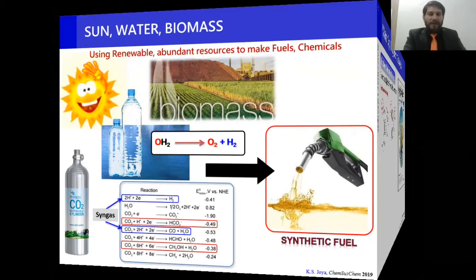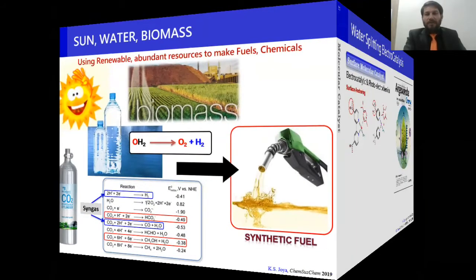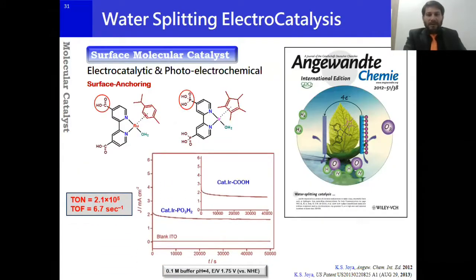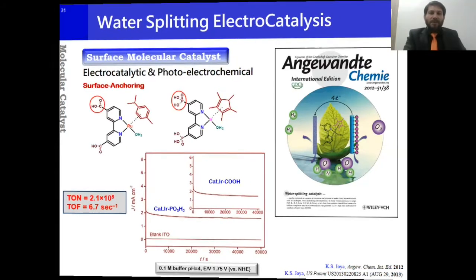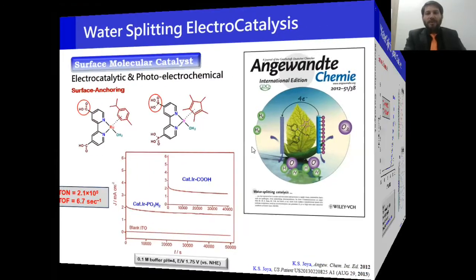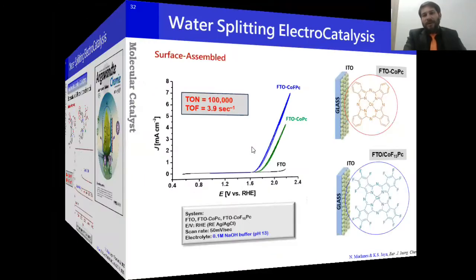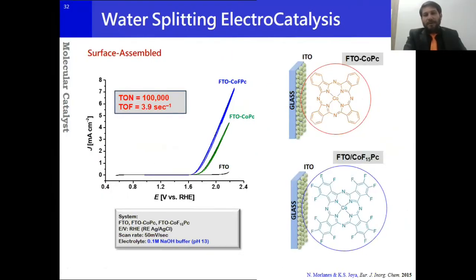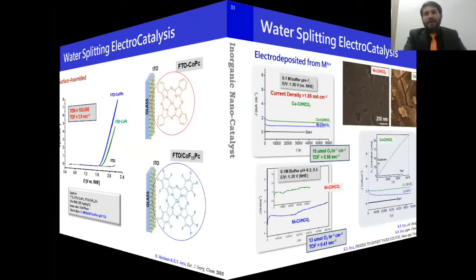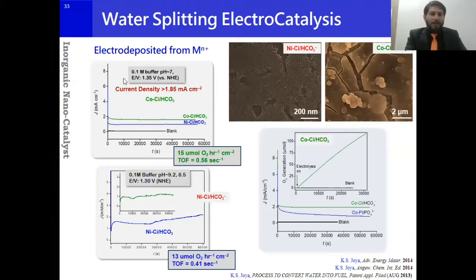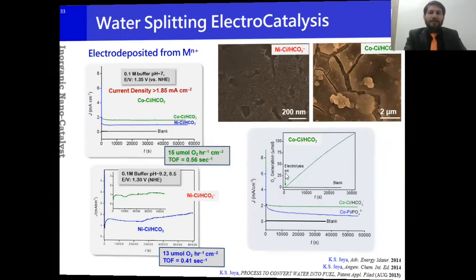So in water splitting, like I said before, we make this organic molecule, we functionalize them on the surfaces, and then we perform water splitting. In this case, you can see these are just molecules absorbed on the surfaces. They can also perform water splitting. And then these are electrodeposited metal oxides. In this case, you can see nickel and cobalt. And you can see from this figure, they perform wonderfully well because they are performing for a long duration of water splitting without almost any noticeable degradation.